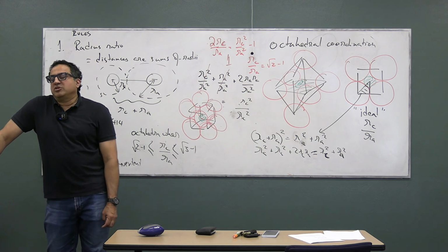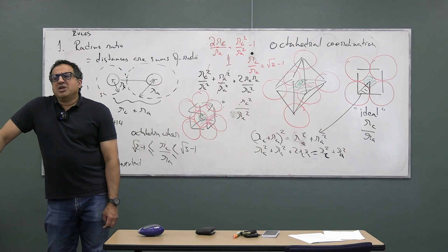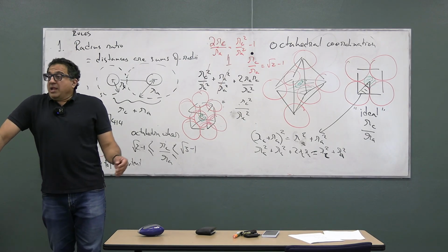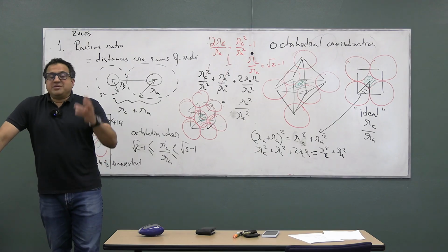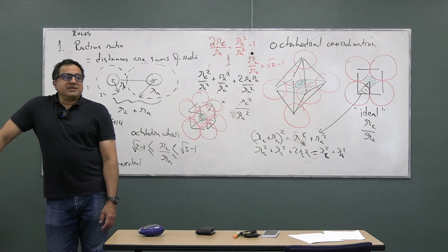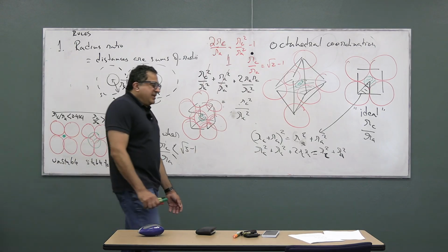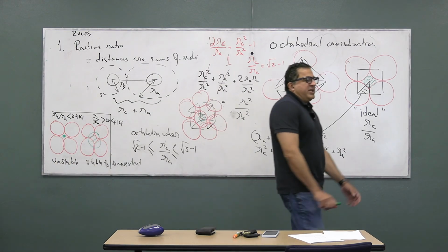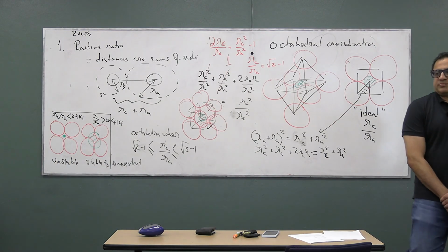Plus 2, plus 3, plus 4. It sort of skips 5 and 6; those are not common. But 2, 3, 4, and 7 are not uncommon. So as you go from 2 to 7, the manganese ion is getting smaller and smaller. When you look at these tables, it will tell you what the radius is, given the charge and given the number of neighbors, the coordination number.